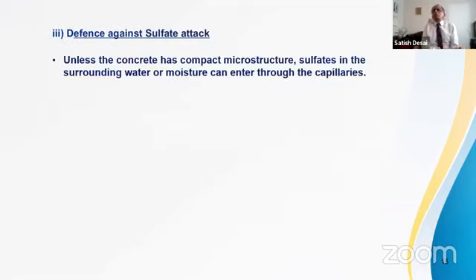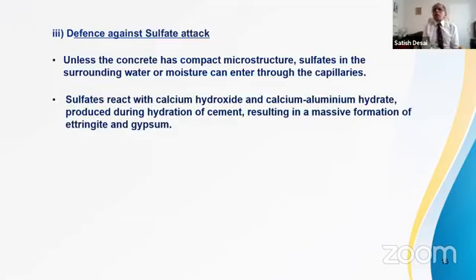Sulfate attack. If concrete doesn't have compact microstructure, the sulfates in the surrounding water, moisture can enter through the capillaries. Sulfates are found in spray of seawater or often in the underground water. So tests have to be made to make sure, but if sulfate enters, it reacts with calcium hydroxide and calcium aluminum hydrate, which are produced during hydration of cement. What happens is massive formation of ettringite and gypsum.